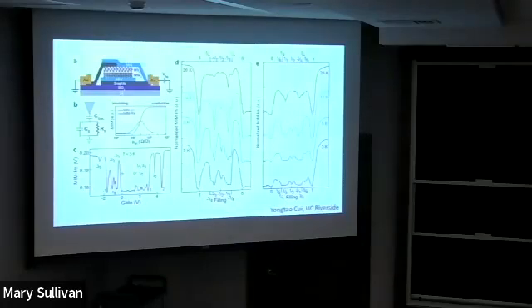So we believe this is a very rich system for strong correlation, but we cannot do the conductance measurement to see this, right? So what do we do? We actually found a collaboration with Cui's group at UC Riverside. What we do is make this structure just like the other groups. Cui's group has this microwave impedance microscope, which can locally measure the conductance without worrying too much about the contact resistance. As a result, this is a typical spectrum you see, each dip corresponding to a conductance minimum.